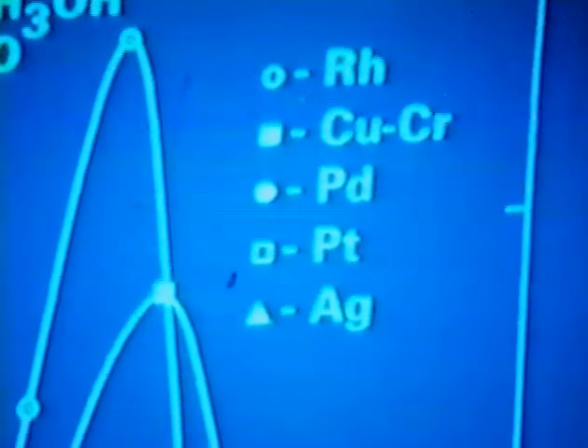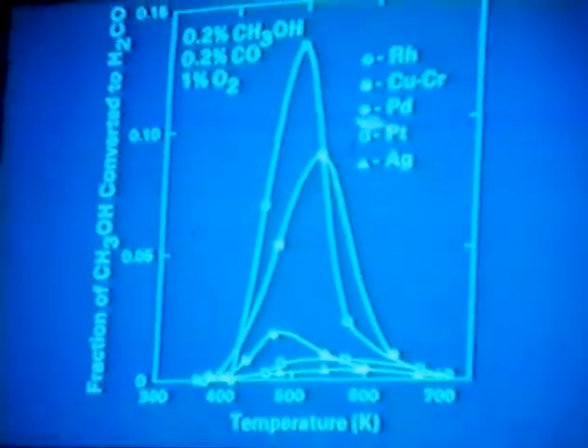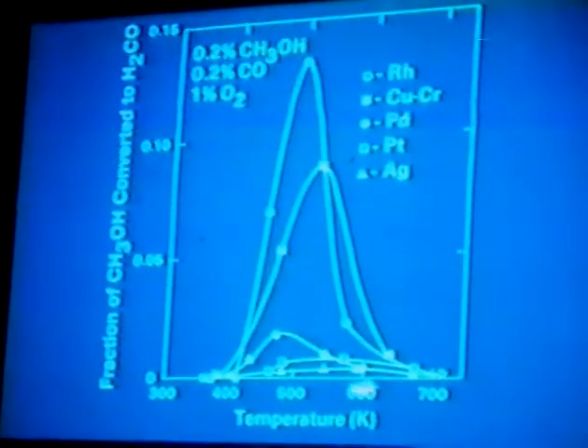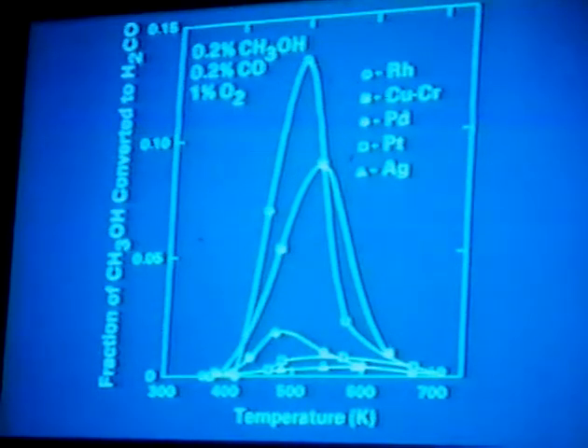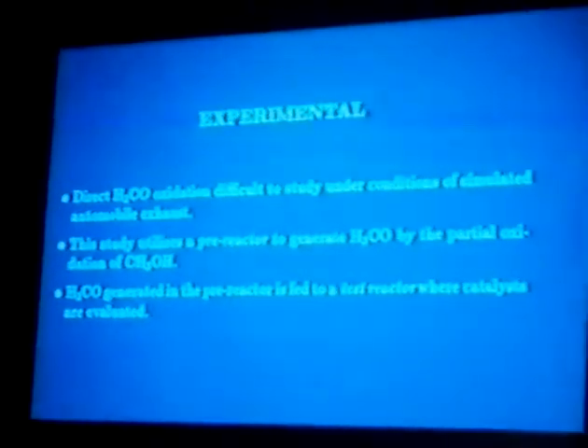Secondly, you notice that all the curves have a maximum in the formaldehyde production. I think this is indicative of a series-type reaction mechanism where your methanol is first partially oxidized to formaldehyde, and then the formaldehyde can further react to form CO2 and water. One of the things we found, that 2 of the more attractive catalysts for methanol oxidation were platinum and silver-based catalysts, which, as you can see here, give very low yields of formaldehyde. But this data tells us nothing about the activity of these catalysts for the direct conversion of formaldehyde. And so that was the basis of this additional work that we've done.